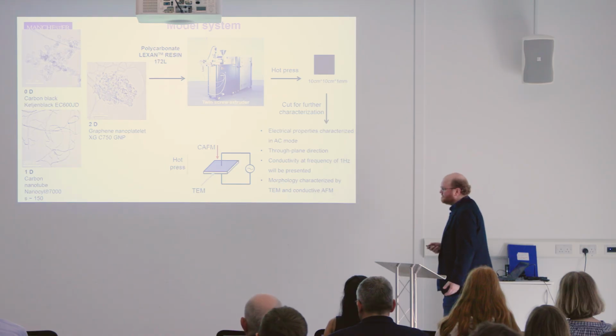Because what industry doesn't want is, when they buy a masterbatch and they're making these, to add slightly too little polymer or slightly too little filler and it's not conductive, or maybe it's too conductive. They want it to be idiot-proof, so that if they give a customer the recipe and say, this loading, this filler, this mixing method will give you the properties you want, it isn't too sensitive. So we thought, let's look at how we can change the shape of this curve, and also how carbon blacks and nanotubes compare to graphene, and whether there is any synergy between them.